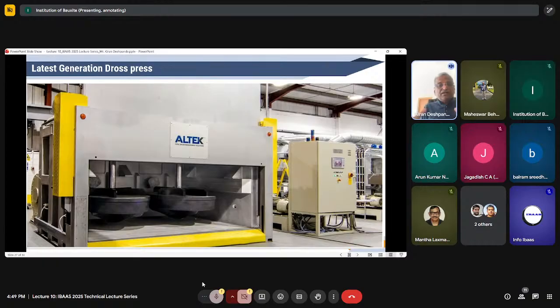These are the two DROSS presses where you can have enhanced capacity, and the DROSS pans are two. In one DROSS pan, there are two compartments. So you can skim more DROSS in two compartments and you can press simultaneously. On the right side, you can see the hydraulic power bank, and on the top is a fume extraction. You can imagine the head comes with a hydraulic power of 90 tons. So you are pressing the DROSS at 90 tons in that confined space. All the liquid aluminum drips into the bottom sow mold in less than 6 minutes. So in 6 minutes, if your DROSS is 1 ton, you can recover 250 kg aluminum, rather than spreading on the shop floor and making it dirty, with fumes coming out and an unhealthy, dusty atmosphere. Everything is stopped. Next slide.